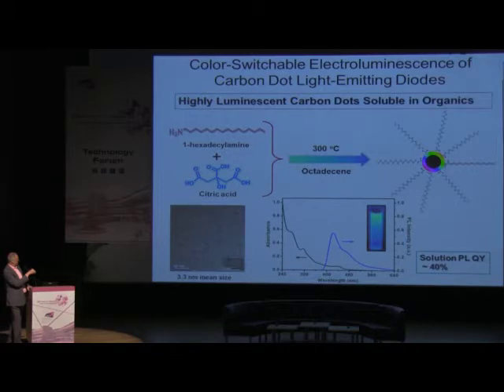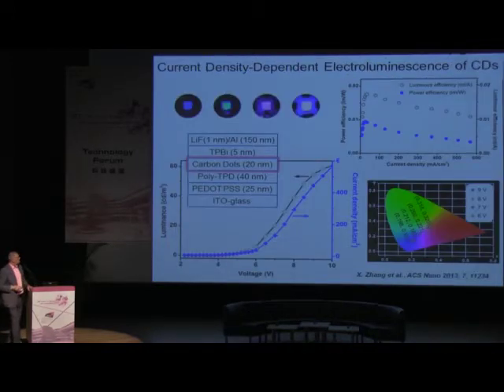So these particles are slightly larger, 3.3 nanometer mean size, still nice blue emitters, like you can see here. Solution photoluminescence quantum yield very reasonable, 40%. And then this work has been done actually mostly by my postdoc here, but he is at the same time associate professor in the University of Jilin. And they have all the facilities to fabricate LEDs over there.